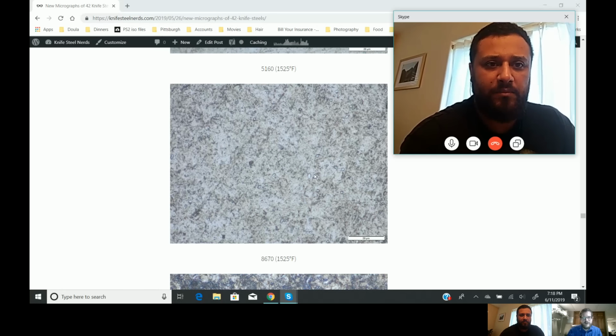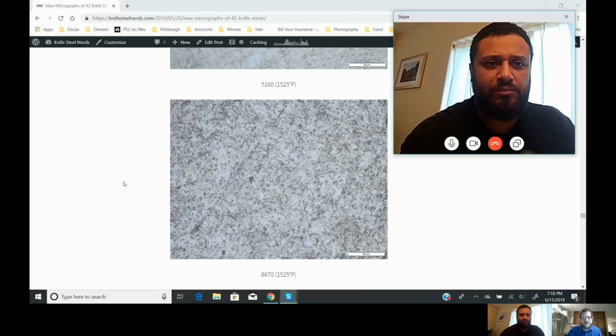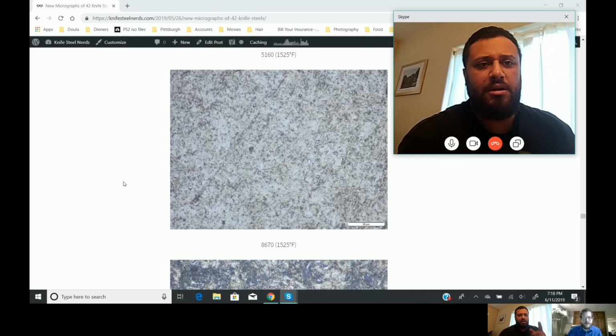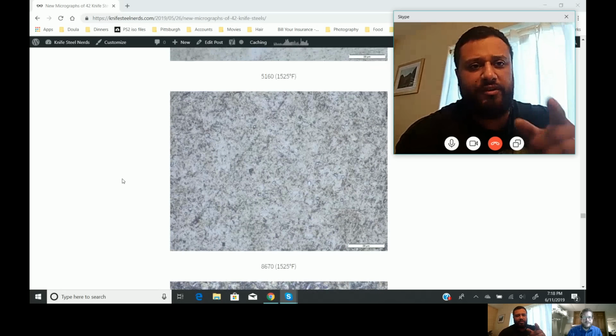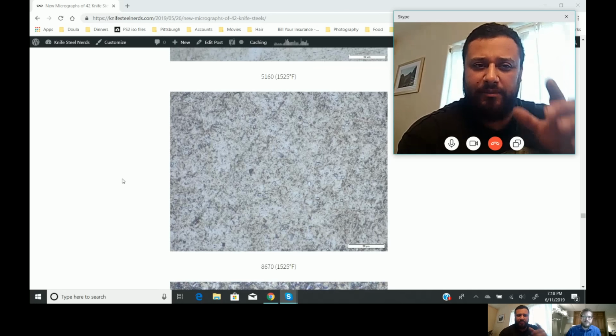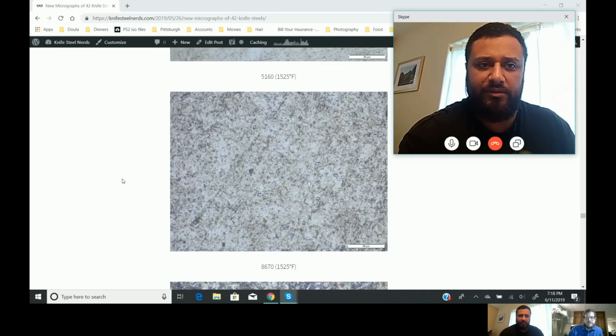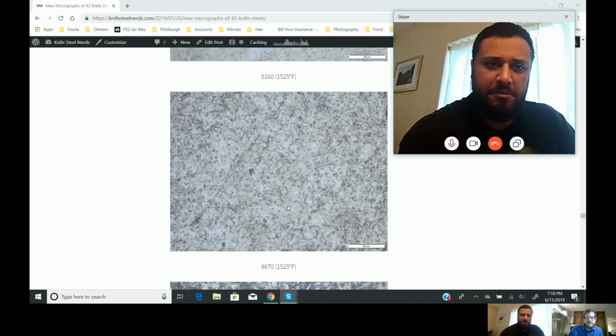8670, you can see a few stray carbides in there, still pretty low for carbide volume. And we measured its toughness. It's just as good as 5160, if not a little bit better. Now this one was interesting too, because that actually looks a little bit similar to the Z Tough or 3V as far as the carbides we can see, right? Yeah, some of these carbides are visible.